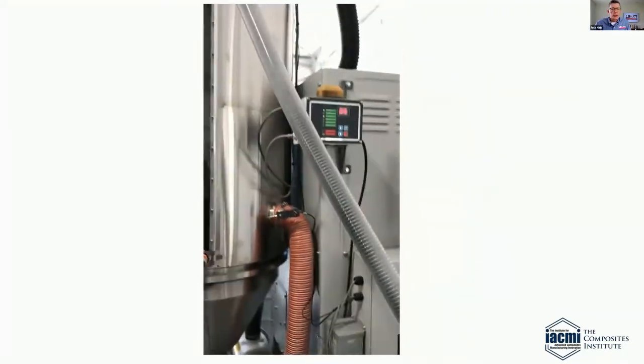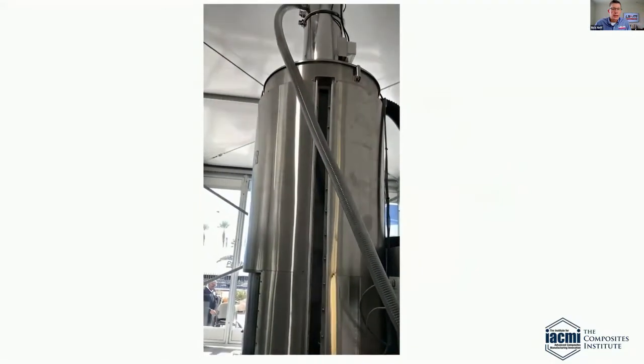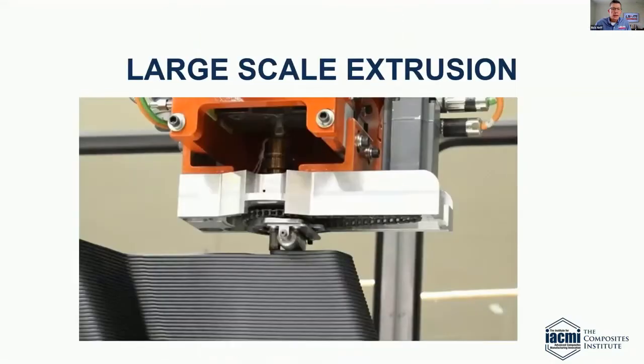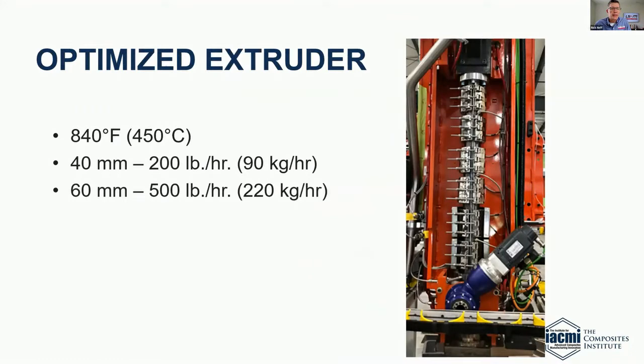The pellets need to be dried before they're processed. So they're drawn up with a vacuum into a commercial dryer, and then they're extruded in large beads by the system. Now, what's interesting about THERMWOOD is that they have an optimized extruder for large scale additive that has two melt cores. One is 40 millimeters, another is 60 millimeters. The 40 millimeter can put out 200 pounds per hour, and the 60 millimeter is 500 pounds per hour. The little desktop machines aren't near a pound per hour, so this is very much larger.